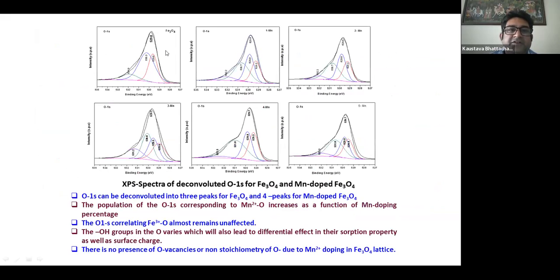Now, equivalently, if we check the oxygen also, for Fe3O4 we'll have peaks that can be correlated to the lattice oxygens at 529, 530, and 531.1. So basically, it can be correlated with the oxygen that is bound to one Fe+2, one Fe+3, and another will be the hydroxyl group. Because in the Fe3O4 system, we can directly see that there are no oxygen vacancies present. So that is quite pertinent from here. And equivalently, once we dope with the manganese, there's one more peak for manganese-oxygen also. So we'll have oxygen being attached to Fe+2, Fe+3, and Mn+2.